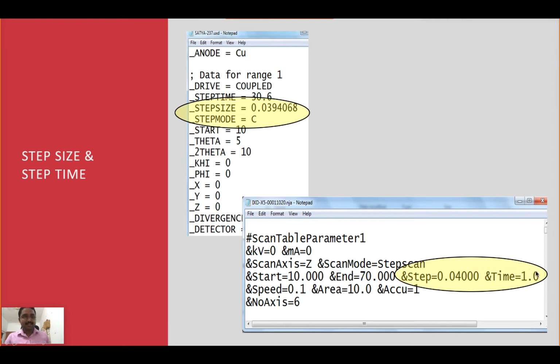Similarly, if the time is 1 second and I increase it to 2 seconds, what will happen? The detector will remain in a step for 2 seconds. So you can imagine proper data is obtained, very good intensity data at that particular step. But there is a catch here. If you decrease the step size, then the time for obtaining your data increases. If you are getting the data in half an hour, and you decrease the step size by 2, you will get data in 1 hour. Similarly, if you increase the time by 2 seconds, again double the time will be taken.